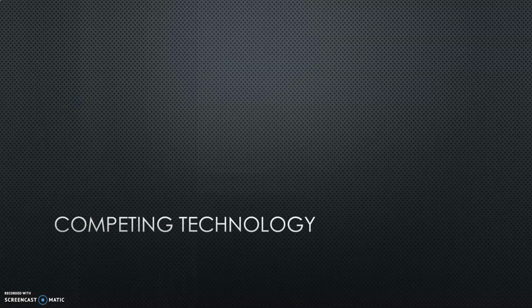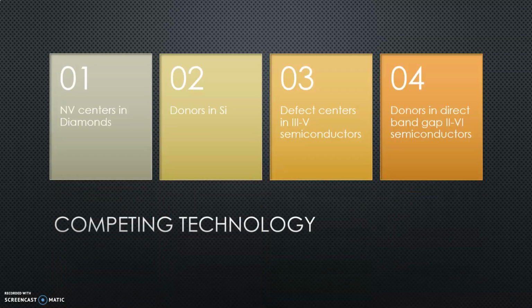Before I go into the further details about the technology, I want to do a thorough discussion of the existing competing technologies and what are their disadvantages as compared to zinc oxide. Here is the list of existing technologies and their comparative disadvantages. First we discuss NV centers in diamond. While NV centers in diamond have the biggest advantage of having the ability to operate at room temperature, they do have certain disadvantages. Mainly, the entanglement generation in NV centers is typically low and limited by non-ideal optical properties such as optical inhomogeneity, spectral diffusion, and low zero phonon radiative efficiency.